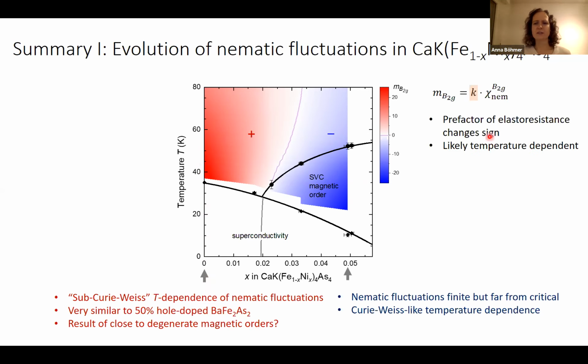Overall, most striking here is that we have an example where the prefactor of the elastoresistance changes sign in composition and temperature in a phase diagram, and also becomes likely temperature dependent, at least in a part of this phase diagram. So to come to the second part of my talk, which will be a bit shorter, is,